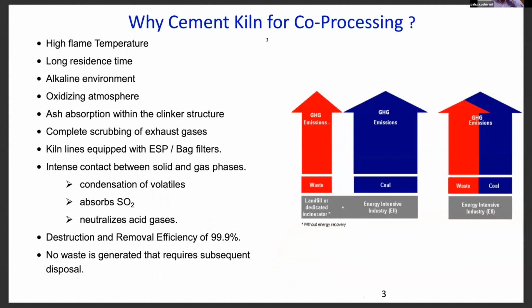Now, why is the cement sector suited for co-processing of alternative fuels, particularly municipal and industrial waste? The main reasons are that the cement sector, having a temperature of around 1500 degrees Celsius inside the rotary kiln, provides a very high temperature, a very long residence time, and a very alkaline and oxidizing atmosphere, which results in a destruction and removal efficiency of 99% or 99.9% of all the toxic elements. And the ashes created during combustion are also fully absorbed in the clinker structure. So there are no wastes as such.